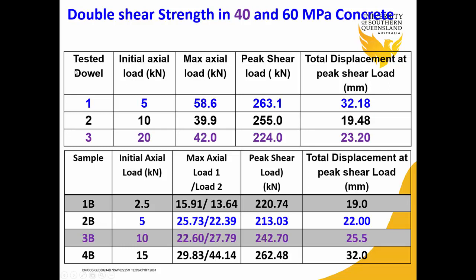The value of shear strength, peak shear strength, and shear displacement corresponding to peak shear load for 40 megapascal and 60 megapascal concrete block are shown in these tables. The table on top is for 40 megapascal and below is the 60 megapascal concrete block.